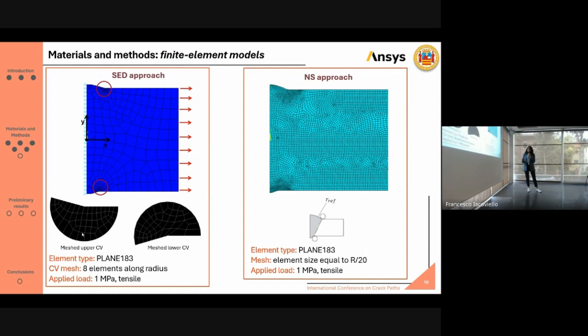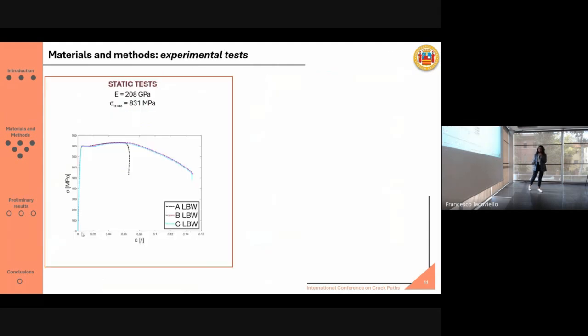And here the notch is considered as it is, while, as anticipated, in the case of the notch stress approach, we have a blunt notch, so we consider a reference radius and a control radius, which is slightly larger. So the radius is 1 millimeter and the control radius is 1.1 millimeter. And so around the notch, we have an element size equal to R divided by 20, where R is the 1 millimeter radius. The applied load was simply a tensile load of 1 megapascal for reproducing the mode 1 loading.